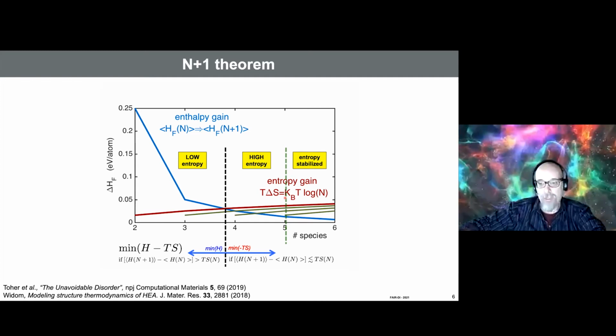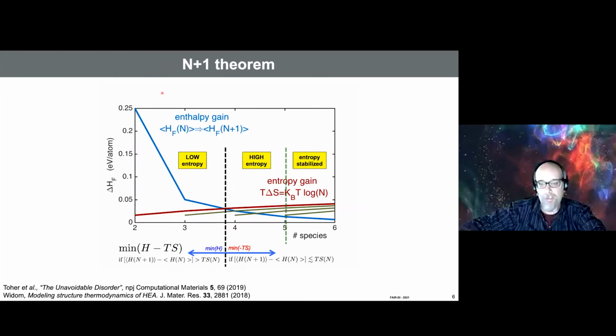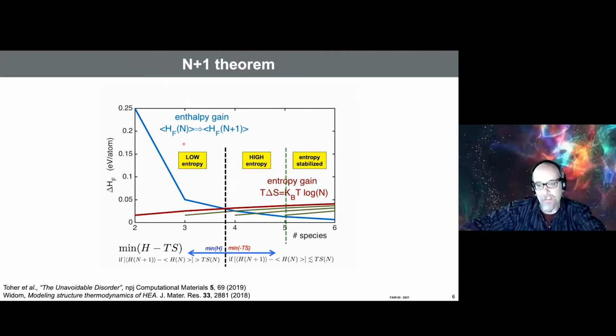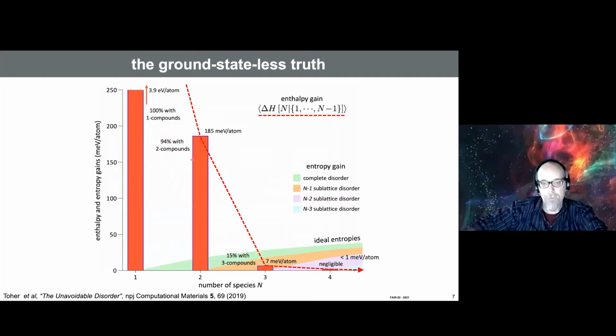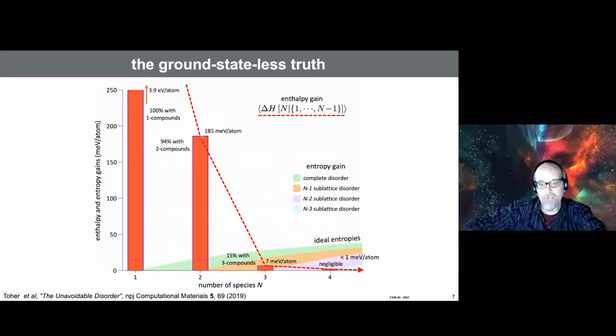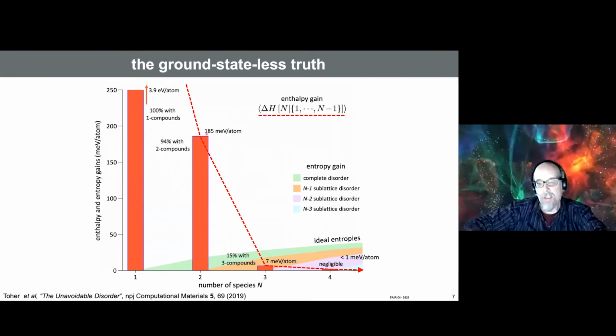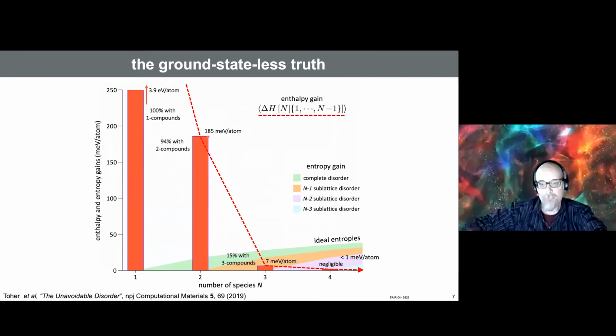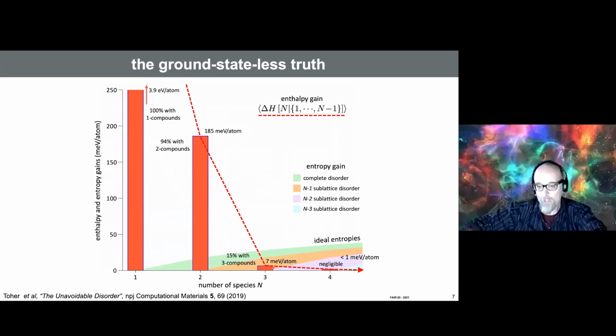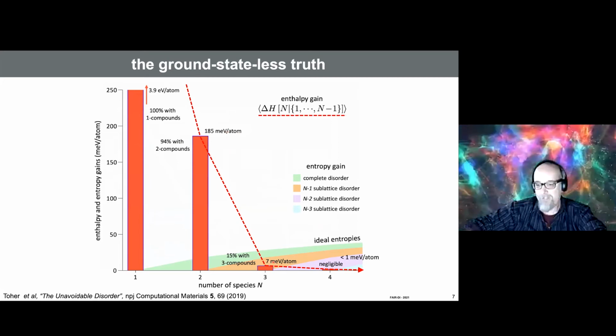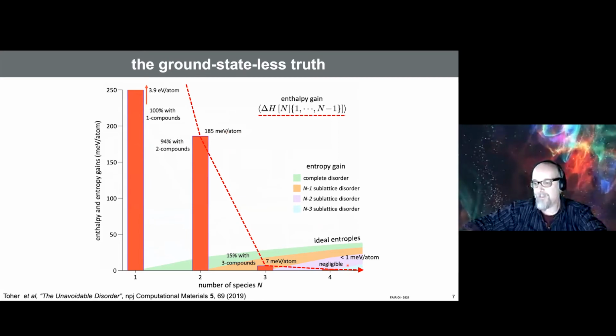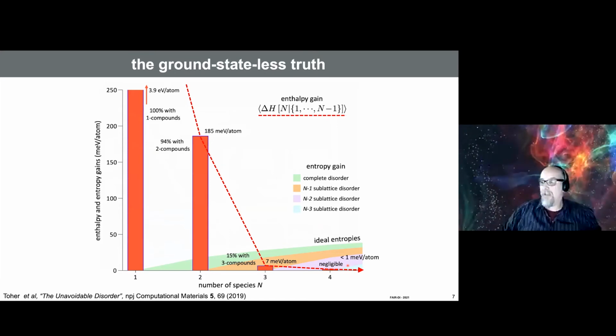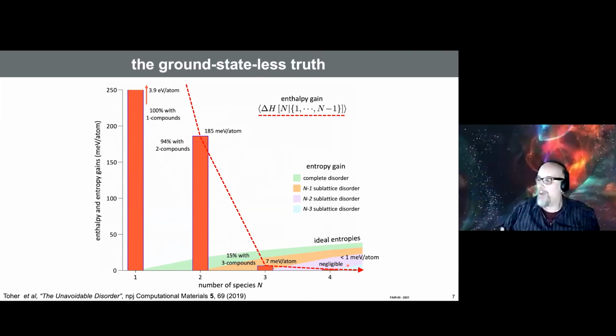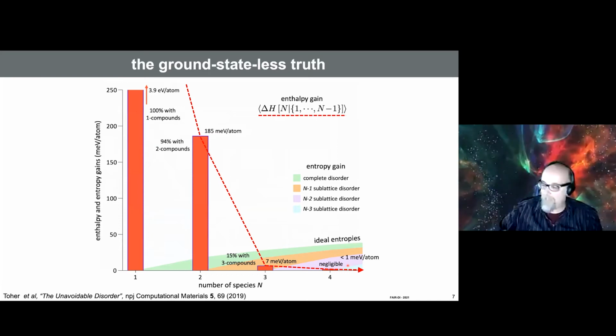Okay, so now the real numbers. This was like a cartoon. The real numbers is this. Okay, so if you mix two species, the expectation of formation enthalpy is 185 milli-electron volt. If you mix 3 species, it is 7 milli-electron volt. If you mix 4 species, it is less than 1 milli-electron volt per atom. And that's why, at least these are for metals, an example.